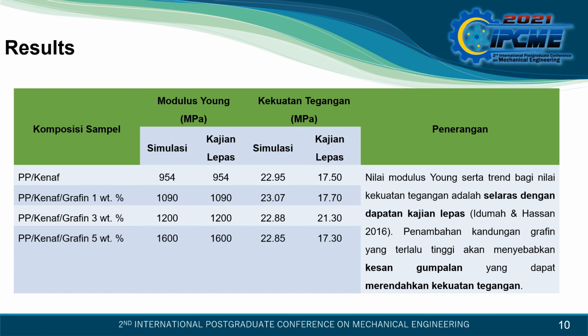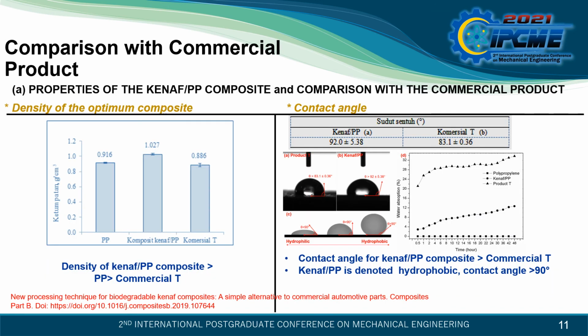The reason here might be due to agglomeration. When there is more addition of graphene, it would cause an anisotropic phenomenon, which unfortunately causes many more cracks during the process. We also did some comparison with a commercial product, and you might see here that our polypropylene is much better than the commercial products in terms of contact angle and water absorption.